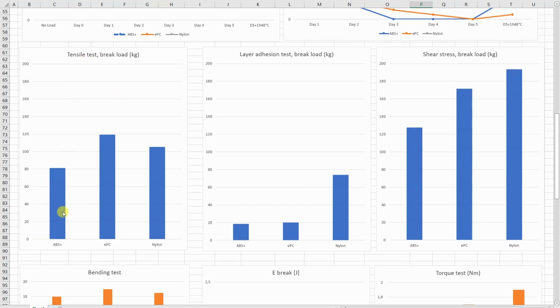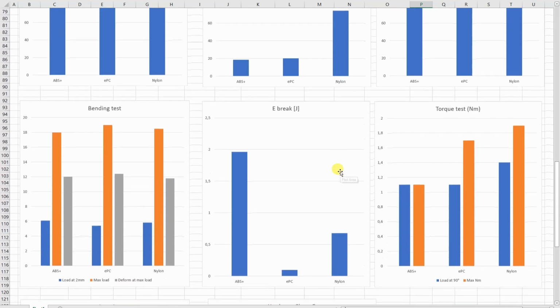Tensile test, no significant difference here. Until the layer adhesion test. These two, ABS and PC, were quite disappointing, until the nylon really impressed me. So this is quite big for the layer adhesion test. This scale is 200 kilograms, so we can compare them. But shear stress, I don't think it is too important for these applications.